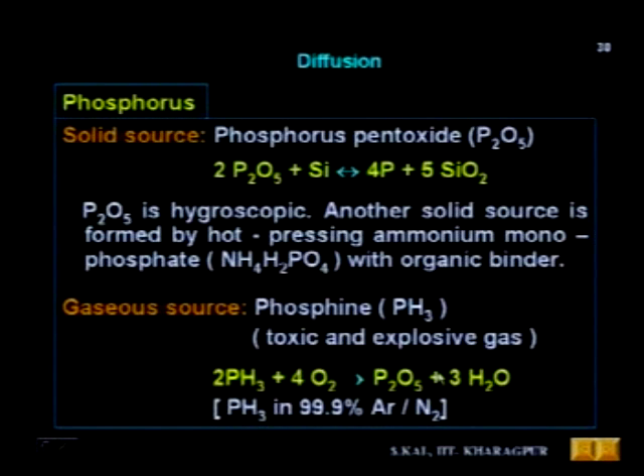First, whatever form the source is, either gaseous, or if it is a liquid, then it will be a halide. The halide of the phosphorus atom is POCl3, we will see it, and that has to be converted initially to phosphorus pentoxide, P2O5, and then that P2O5 reacts with silicon at high temperature. It will form individual phosphorus atoms which will diffuse, and silicon dioxide which will form as a glass, which you can easily remove by hydrofluoric acid.